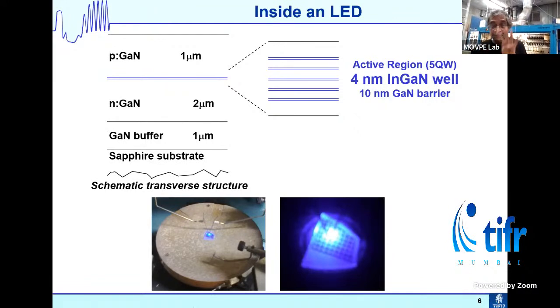On sapphire, we grow gallium nitride, about 1 micron thick. 1 micron is again 50 times thinner than your hair, or 100 times thinner. If you have nice thick hair, for me it will be 50, for you it will be 100. Then you grow some N-type gallium nitride and P-type gallium nitride, and in between the two you have what are called quantum wells. Quantum wells are very, very thin layers of semiconductors. We have indium gallium nitride, 4 nanometers thin, separated by 10 nanometers. This is the region that emits light. And by controlling how much indium I put in the indium gallium nitride, I can control the color.